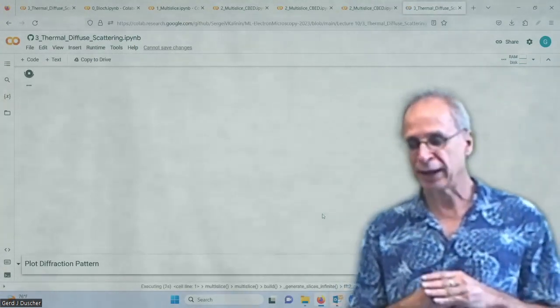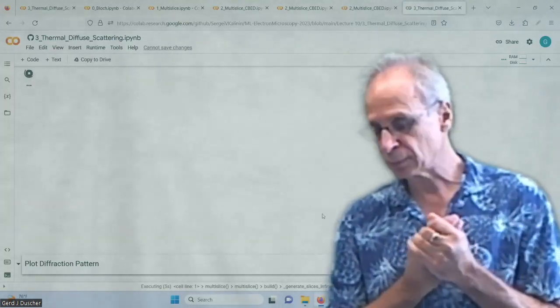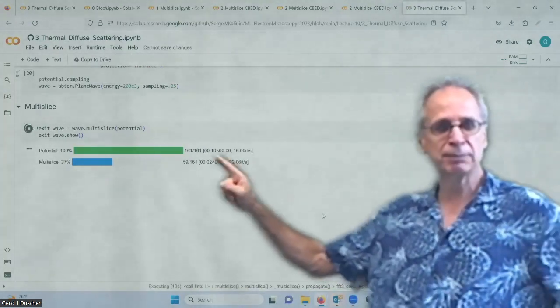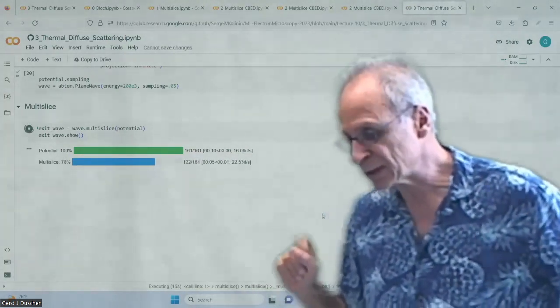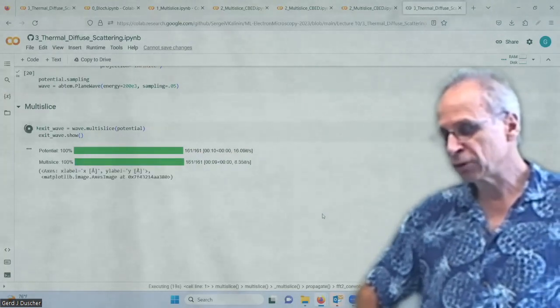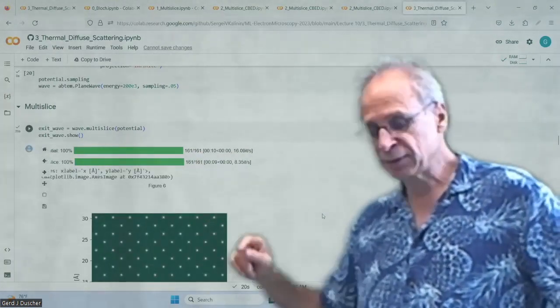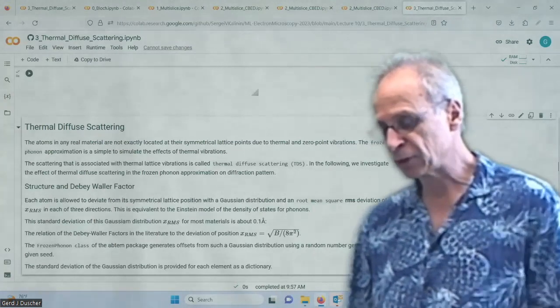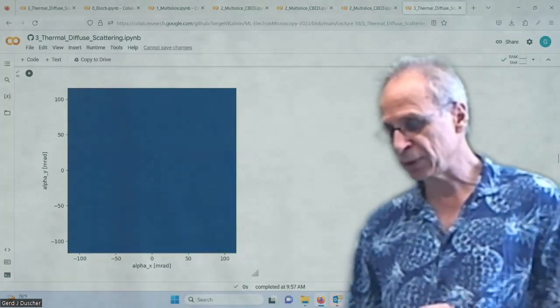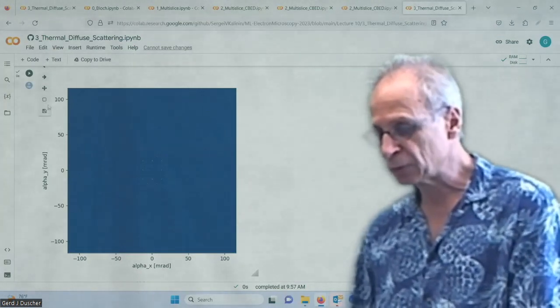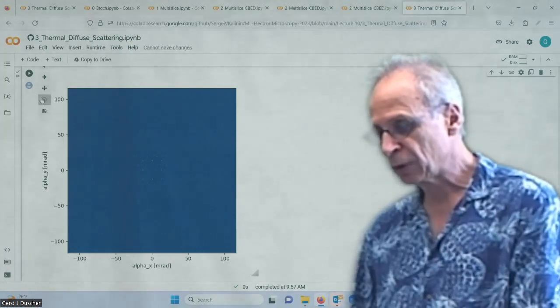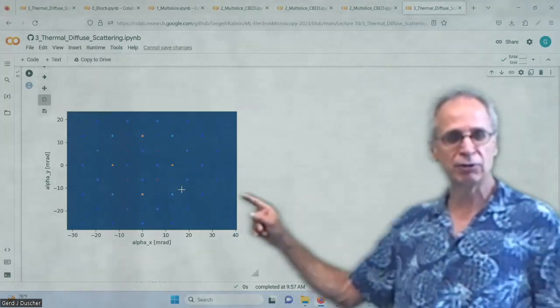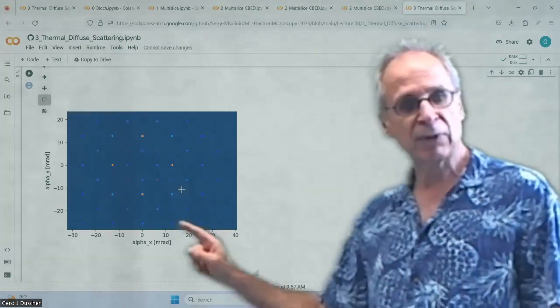We make an exit wave. Building the potential took about 10 seconds, and we go through the different slices in another 10 seconds. Then we plot the diffraction pattern. The diffraction pattern should be the same thing we got before. Our incoming beam was a plane wave and we have the different intensities in the diffraction pattern. We can notice the reflections here — the forbidden reflections that we got. But now we have to introduce the thermal diffuse scattering, because the atoms are not sitting in their perfect positions — they always move around.